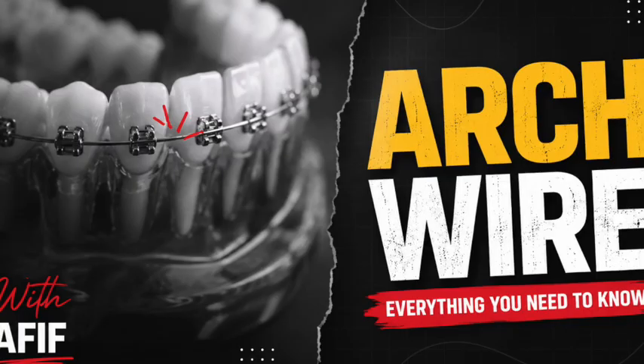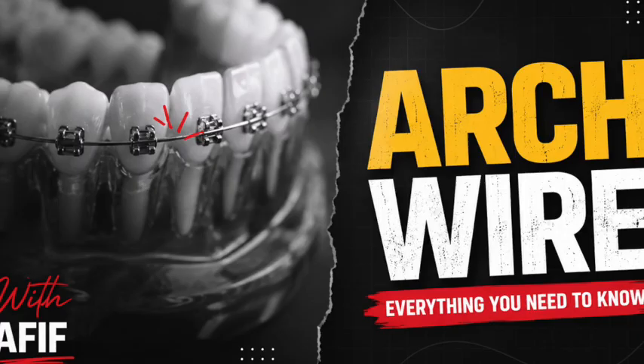Gold alloys were the only materials sophisticated enough to survive intraorally for months or years without oxidizing, rusting, and degrading into toxic byproducts. Because nobody wants toxic rust in their mouth. Definitely not. But as the historical texts extensively document, gold had massive biomechanical drawbacks. Because it's soft. Right? Exactly. Gold is fundamentally a soft metal. Even when metallurgists alloyed it with platinum and copper to toughen it up, the yield strength was pitifully low. So it would just bend and stay bent. Yep. The springiness was practically non-existent, and the financial cost was, frankly, astronomical.